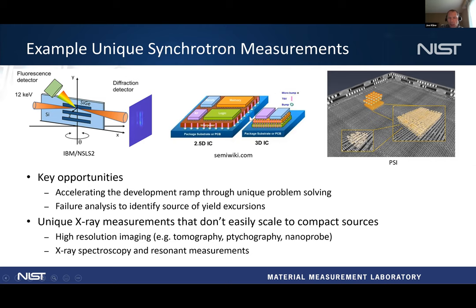In this particular case, I don't have any data, but this is for advanced packaging where you have chips that are stacked. Particularly when you go to smaller and smaller scales of the connections between them, like copper-copper bonding, and you get down to a couple micron pitch on the structures, you suddenly have millions of connections between these dies that are stacked on top of each other. And they need to be able to image those million connections to make sure all of them are connected, or if any of them fail, they need to be able to see that. So they do quite a bit of X-ray imaging on that.